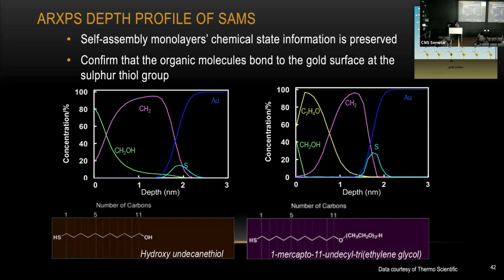So we tilt the sample about 10 degrees, 20 degrees, 30 degrees, multiple times. For our machine here, we can tilt between 0 to 70 degrees, and that can pretty much give you the entire region of the top 10 nanometers of your sample. So you can see different signal intensities accordingly based on the chemical structure over here. Finally, the substrate is gold, so you simply see a gold signal. The measurement for this one is just to prove how the organic molecule is binding to the gold surface. It simply relies on the thiol group, and the signature is a sulfur peak right here. It's just between the coating and the substrate, you see some sulfur signature.